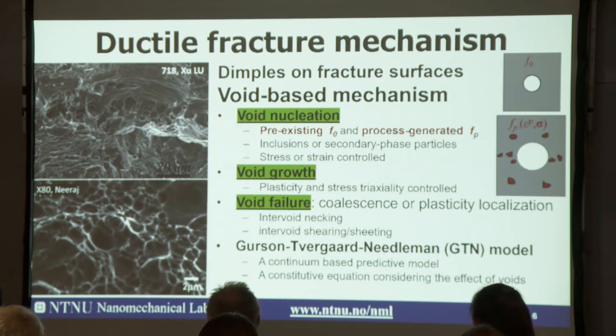Void failure could occur in the form of inter-void necking, or in the form of inter-void shearing, depending on the stress triaxiality. So these are quite well known, well understood. There are many models available to describe ductile fracture. The best known model is called the Gurson model, or GTN model, after Gurson, Tvergaard and Needleman.